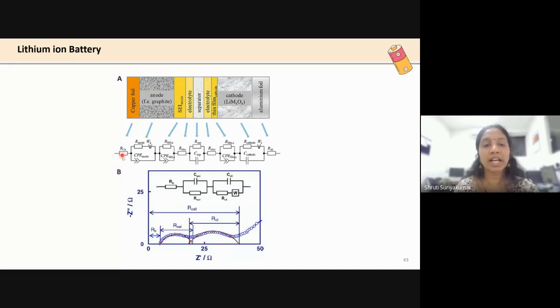A copper foil could have a bulk resistance. A metal wire could act as a resistor here, depending on the resistance it has. And then you have a graphite anode, that you can associate to a kind of a Randles circuit. And then you have an SEI that is again associated to an RC double layer material. You have an electrolyte that is just going to allow or block lithium depending on its viscosity and other parameters. A separator may not be involved, but for now we have that also included. And with the electrolyte and the thin film at the cathode-electrolyte interface, you can call it CEI. You have another film here and again a cathode here and an aluminum foil here.